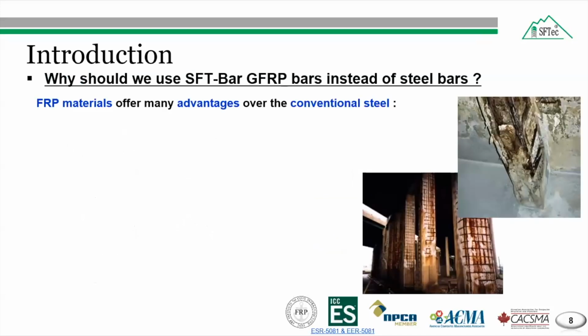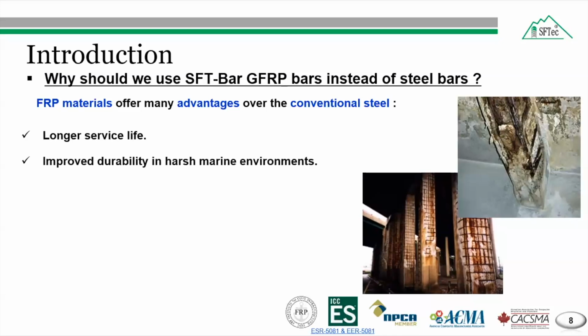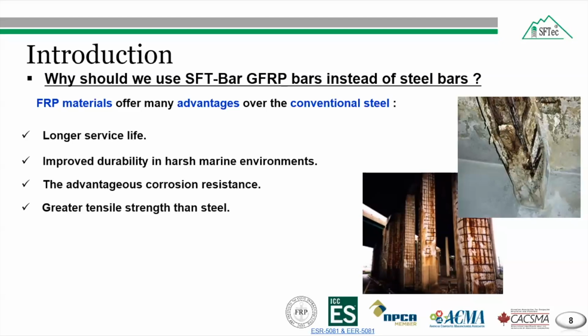So some of the advantages of the glass fiber reinforced polymer bar are that it has a longer service life because of its corrosion resistance. Therefore, there is improved durability in harsh environments such as construction near the coastal area and in Northern American cold climates. So the FRP bar has better resistance against corrosion compared to the steel bar. And the tensile strength of FRP bar is around 2 to 3 times more than that of the normally used steel bar. FRP bars are also lighter due to their low density compared to the steel bar. Their density is around 1/4 of the density of the steel.